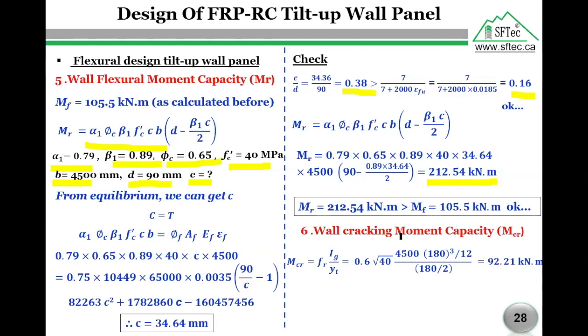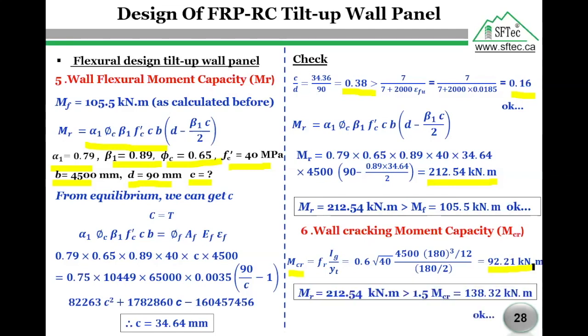The wall cracking moment capacity can be calculated using this equation. So finally, we have M crack equals 92.21 kilonewton meter. By comparing the wall cracking moment capacity and the wall flexural moment capacity, the wall flexural moment capacity exceeds 1.5 times the wall cracking moment capacity, which satisfies the requirement by the Canadian standard S806 for the flexural design.